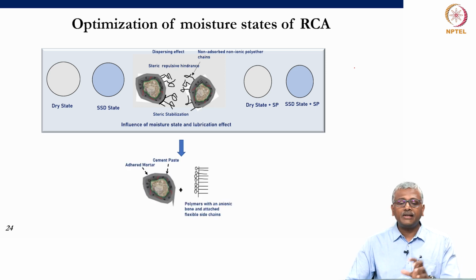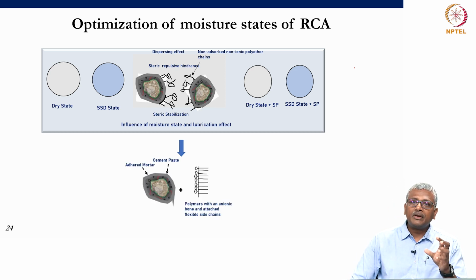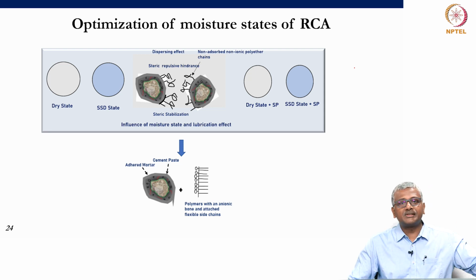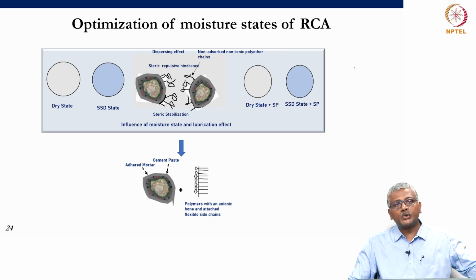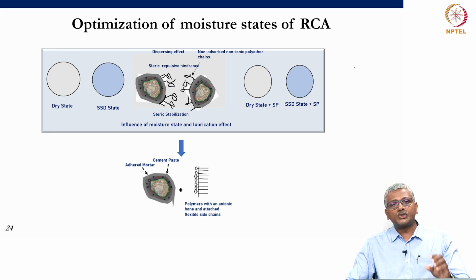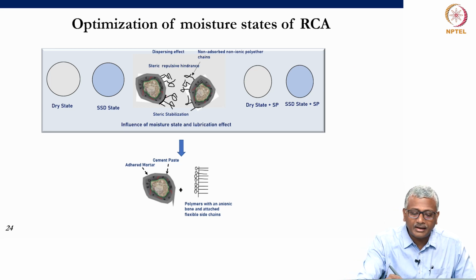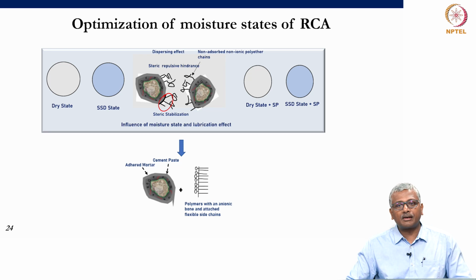So, generally the use of superplasticizers will improve the lubrication effect not just in cement or cement paste, but also in concrete, because superplasticizers also tend to get themselves coated around aggregate particles and provide some level of steric repulsion.